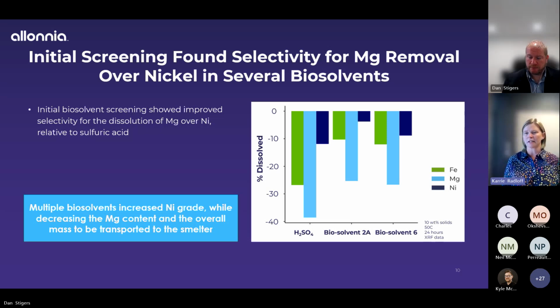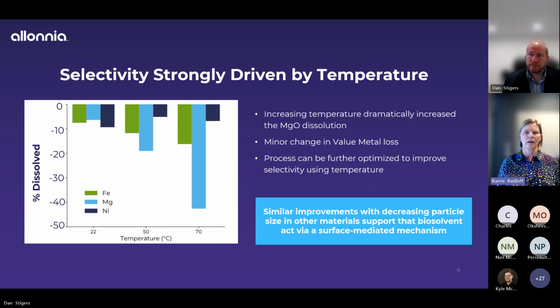Our biosolvents, on the other hand, we can see in this initial test work, we're able to selectively solubilize that magnesium. You can see that in the blue bars. They were also solubilizing some of the iron, which was acceptable in this case, and leaving most of the nickel behind. So this gives us an indication of two biosolvents to look at, and we can look at the things that are similar in their compositions and then start to tune their composition and how we did the extractions.